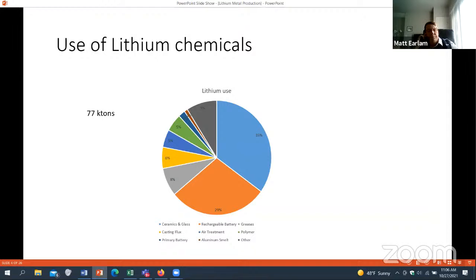Here's just an example of where the lithium is used right now. Typically in the world, there's about 77 kilotons of lithium carbonate produced. Lithium carbonate is the mineral product or the chemical product that's traded in lithium mostly because it's a dry carbonate. It doesn't have waters of hydration associated with it, unlike some other carbonate minerals. About 30% of lithium from lithium carbonate goes into making lithium metal for lithium metal uses, mostly in batteries.